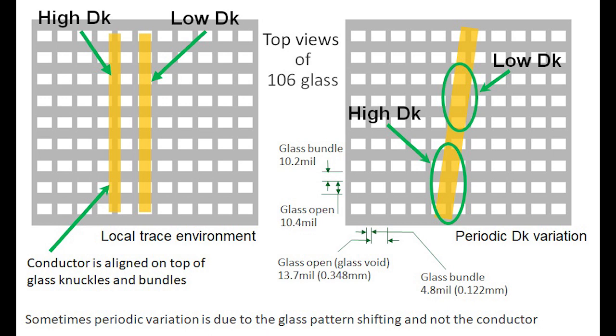How that happens is that in the area I have circled as high Dk, the conductor is going over a region of bundles and knuckles, so it's bundle, knuckle, bundle, knuckle. Then as you move up the trace a little farther, the conductor is aligned to the glass weave in such a way that it's over open, bundle, and that means a lower Dk. At millimeter wave frequencies with very small wavelengths, this difference of high and low Dk in a periodic fashion can cause resonances and even spurious modes to occur. This can be pretty problematic at higher frequencies such as millimeter wave frequencies.